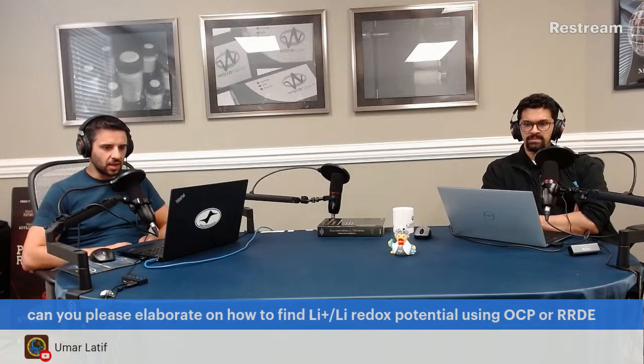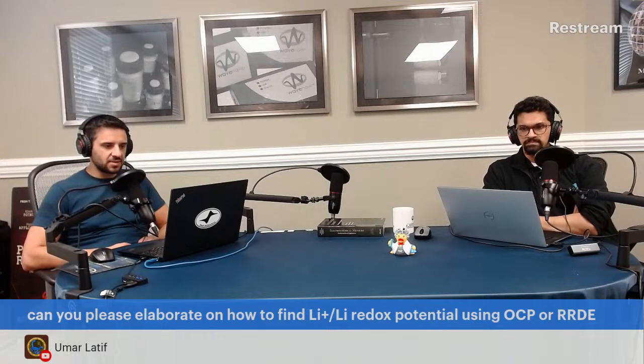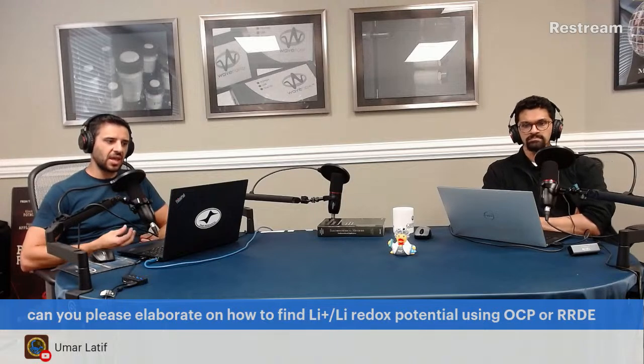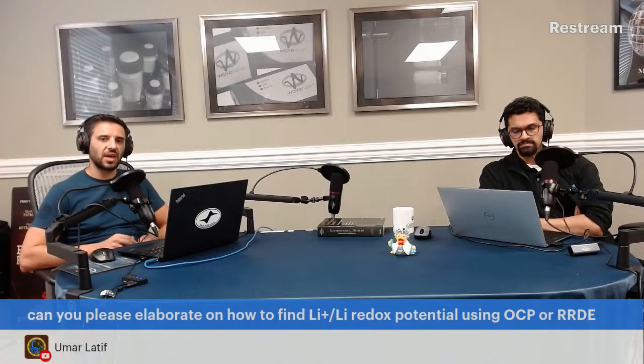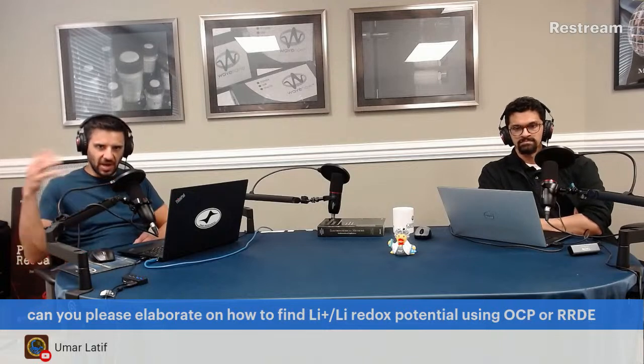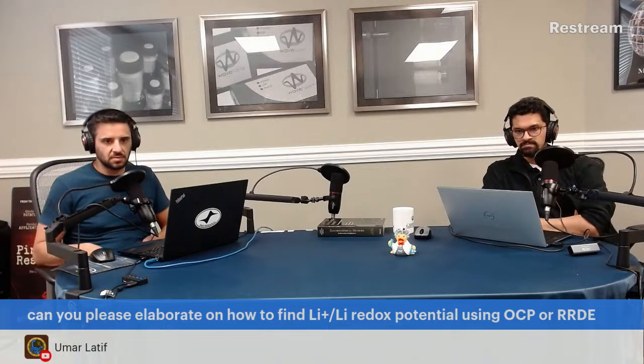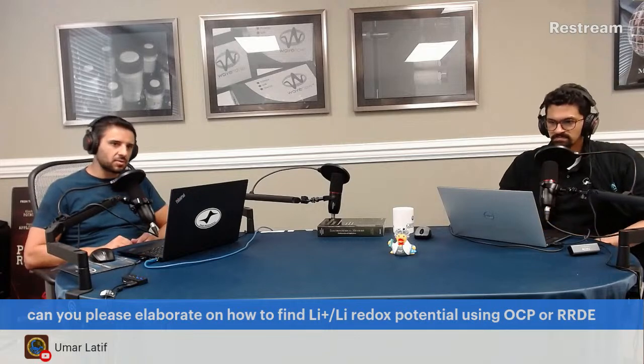And so what it's doing is using lithium as the reference, hence using Li plus as the actual reference, in addition to the counter electrode of the material that you're studying, right? That means it has an infinite source of lithium, basically. Either an anode or a cathode, depending on whether you're charging or discharging, involves a process where it is bringing in or releasing lithium ions. And if you have lithium metal as the other electrode, it's like a perfect source of, or deposit location for, lithium ions to be put into as lithium metal or removed from.